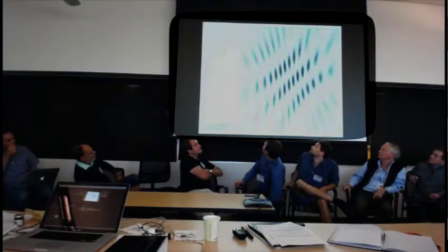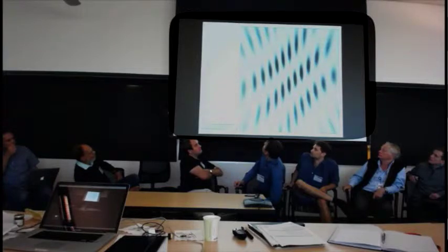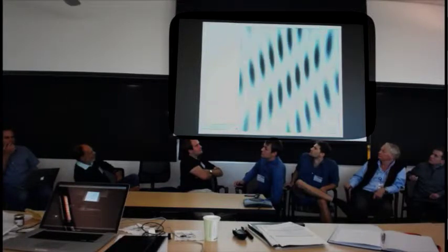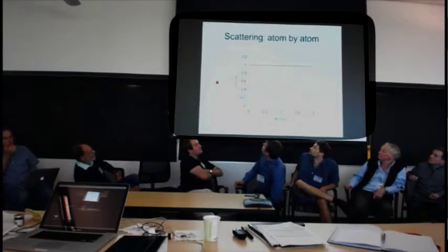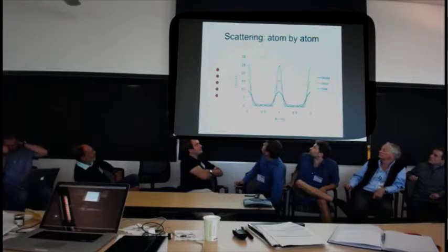Not necessarily ordered correctly. But this is where I try to point out to people that reciprocal space isn't really a reciprocal space at all. It's an angle space. It's just convenient to think of it in inverse angstrom terms, but it's actually an angle. It depends on detector distance. So this is simpler: 1 atom, 2 atoms, 3, 4, 5.